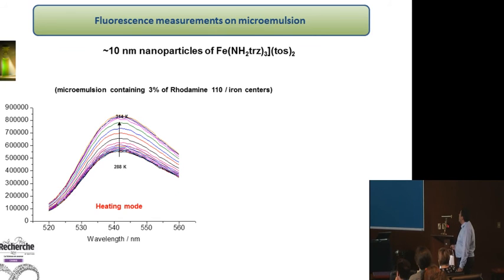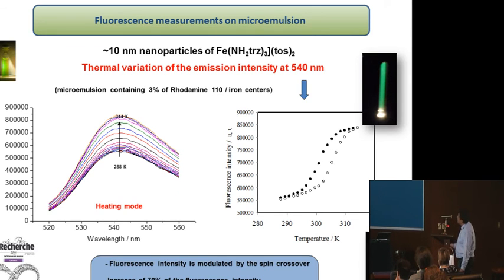Now, if you study the spin crossover properties with the fluorescence measurements, here we have the emission as a function of temperature. We can see that we have modulations, and if we report the modulation at fixed wavelengths, we have this thermal variation of the fluorescence, which corresponds to the spin crossover phenomenon. So we can probe the spin crossover properties using this fluorophore, if you have the good concentration of fluorophore. We can see by eye the color change of the samples. So we have demonstrated a good modulation of the fluorescence by the spin crossover. The increase of fluorescence is quite important, so we can have a good sensitivity.